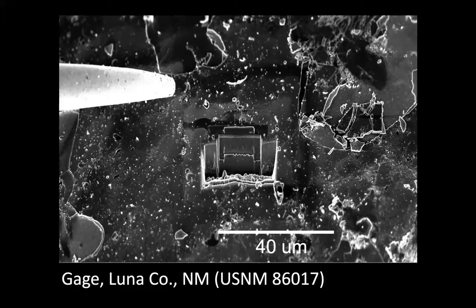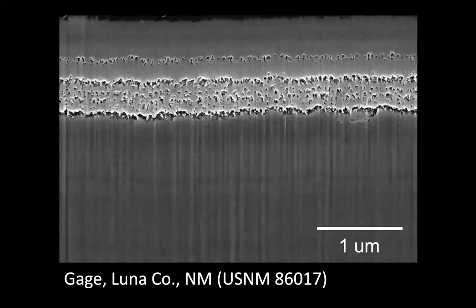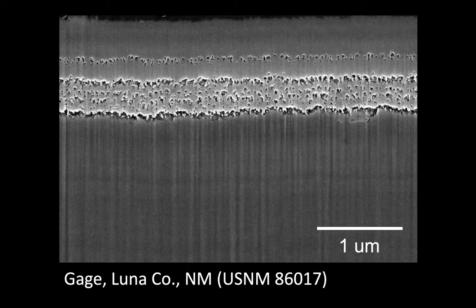So the question is whether essentially we're looking at some kind of a thin film effect with these turgite specimens, and that meant I needed to cross-section through the turgite. So I went to the materials characterization lab here, and Trevor Clark and Kay Wong were particularly helpful for me in extracting a focused ion beam section through this material. And so when we looked at this, this is actually an ion beam image of one of these sections. I didn't really notice a thin film per se, because everything that you see here is goethite, the mineral goethite.